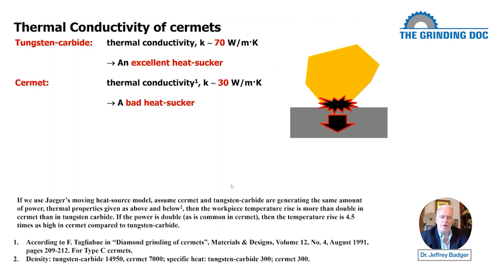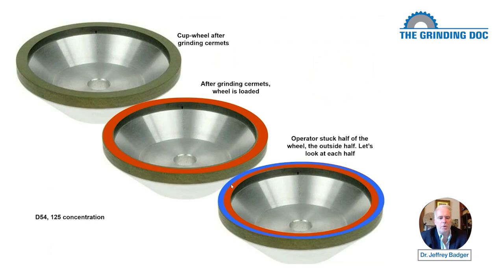So when you grind them, they don't suck away heat. The heat stays there at the surface. That's not even the biggest reason. We could live with that. We could live with the lower thermal conductivity. But what makes it difficult is when we grind, the grits become dull. After grinding CERMETs, we get loading also. CERMETs load the wheel, but we can cope with that by sticking the wheel. Easy. We stick it, we clear away the loading, fine. But what's different about CERMETs is it also dulls the grits.